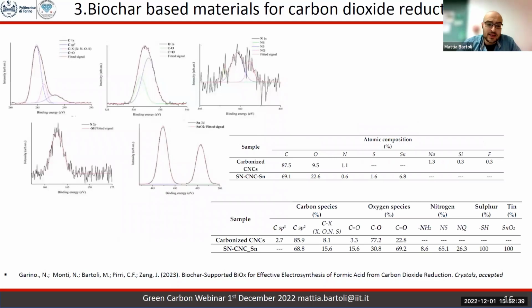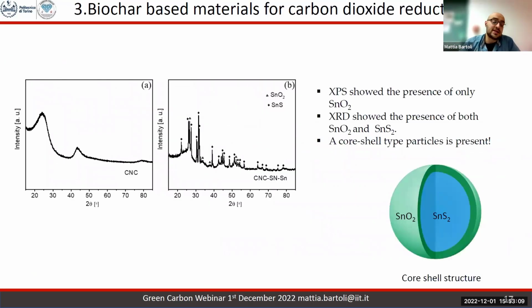Particularly in this case, what we saw by the analysis was that the carbon remained more or less intact, a little bit more graphitic after the tailoring process, but we were able to insert oxygen, nitrogen, and sulfur at the same time, creating a tailoring with the tin particles that you saw before and that we can see here in the XPS spectrum. Furthermore, the XRD analysis shows the increment of graphitization after the tailoring and the presence of a lot of different kinds of functionalities. So in one step, by using a sustainable and scalable technology like microwave approaches, we were able to tailor carbon spheres produced from cellulose with tin oxide core-shell particles, where the core is represented by tin sulfide.